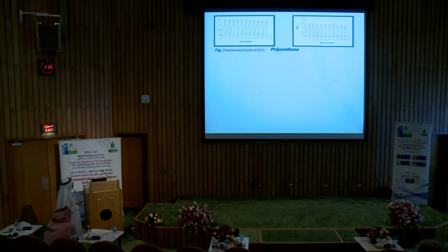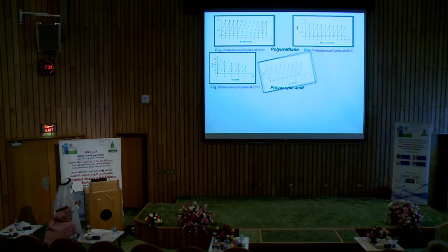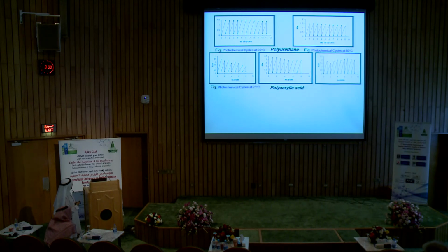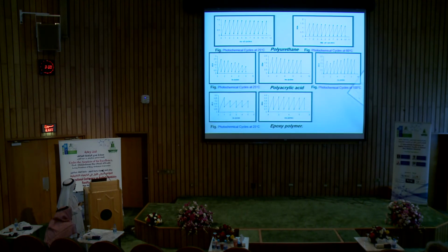This figure shows the fatigue. Fatigue is the term used to describe the ability or stability of the photochromic compounds against the coloration and discoloration cycling. So this compound, in the first figure, we can see that the compound is stable after 11 cycles of coloration and discoloration at 25 and also at 80 degrees Celsius. And this is in polyacrylic acid. This is the fatigue study.